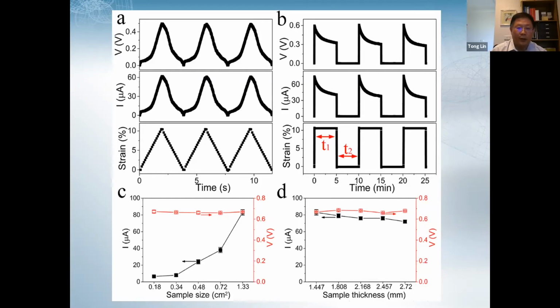If we change the sample size, for example the working area, while maintaining the disc thickness, we typically find the voltage doesn't change much, but the current changes very largely. This result shows that with increasing sample size, the current increases. But if we just increase the thickness, the voltage stays at the same level, but the current is slightly reduced. This reduction comes from the increased internal resistance.